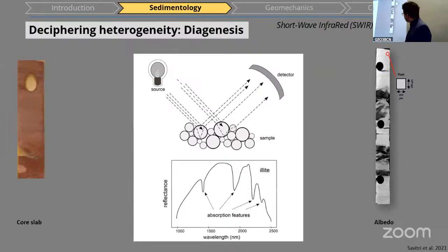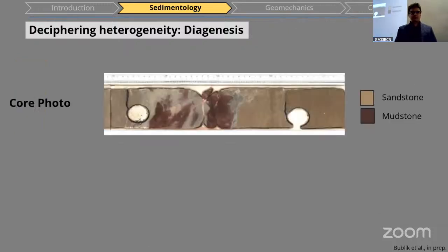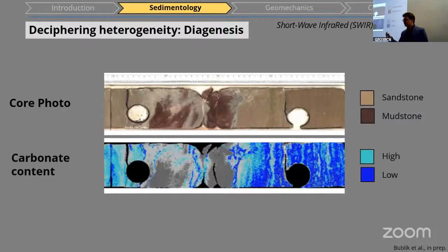And we're trying to make this even better on a smaller scale by using shortwave infrared spectroscopy, where we scan our core slabs using a camera which picks up spectra of the shortwave infrared wavelengths. You can see the wavelengths here. You get a reflectance spectrum for pixel sizes of 200 by 200 microns. And if you analyze these spectra, you can then identify which minerals are present in your sample. And then you can go from a core photo to, for example, a carbonate content. And then you can see it's very heterogeneous also on very small scales, so that you have layers which have very high carbonate content quite closely linked to layers which have nearly no carbonate content. So that makes it for me very interesting. How can we ever be able to predict something like this?